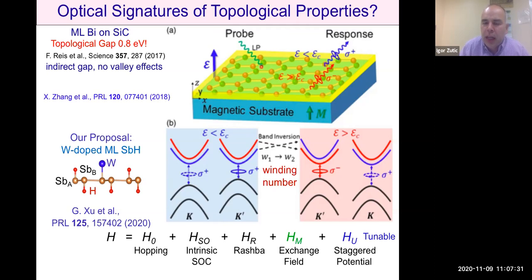So some of the atomically thin materials can be a very, very robust topological insulator. A few years ago, there was a discovery of monolayer bismuthene on silicon carbide, which has a huge topological gap, 0.8 electron volts, about 100 times more than the famous mercury telluride, where the first quantum spin Hall effect was measured. However, this material, even though it's an outstanding topological insulator, has an indirect gap and no valley effect. So for our purposes, it's not very helpful.